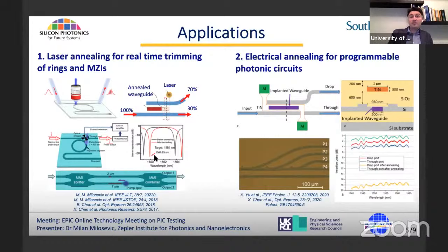This was done, by the way, manually. We managed to position it to 1549.93. We have done a lot of testing of ring resonators, and we always managed to position within 3% of the targeted wavelength peak position. Similar things we did with Mach-Zehnder interferometers. We managed to achieve phase trimming with an accuracy of 0.01 radian. But this work was done back in 2018, and it was done manually.